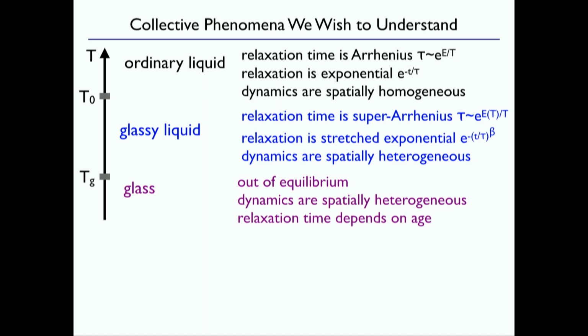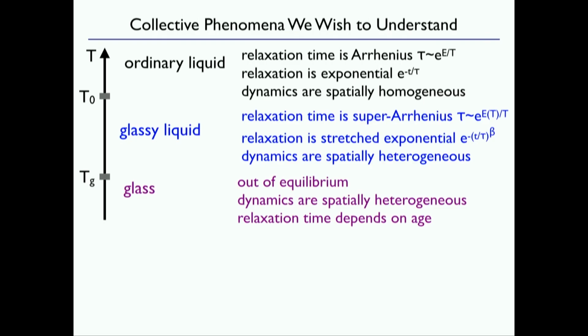So if I quench from a high temperature to below the glass transition, and I look at the relaxation time, initially it's pretty fast, like it was at the high temperature. But the longer I wait, the slower it gets. So it depends on how long I have been there. So it's really out of equilibrium.